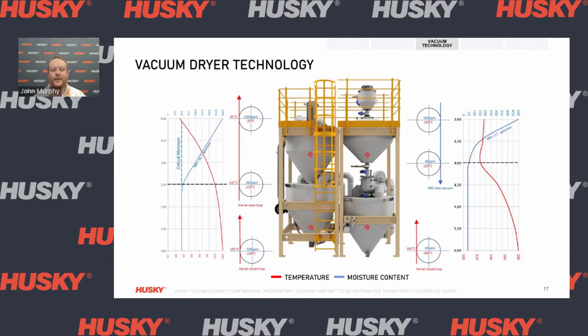And here's where we really start to see a difference in the vacuum technology over a desiccant-based technology. Now we see an even more aggressive curve when it comes to moisture removal. From 500 ppm, we're able to quickly, over the course of an hour, hour and a half, reduce that moisture content down to 40 ppm. During this stage, there's a very, very small reduction in temperature just because of the evaporation of that water.